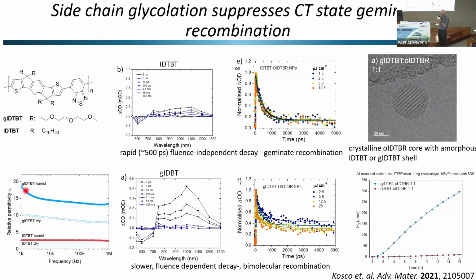This is the relative permittivity of a glycolated donor. This is IDTBT. When you glycolate the side chains, they swell in water, so the water uptake leads to a very high relative permittivity. In other words, the dielectric constant is increasing. When it increases, it stabilizes the charges and helps separate them. So this is a very interesting system.